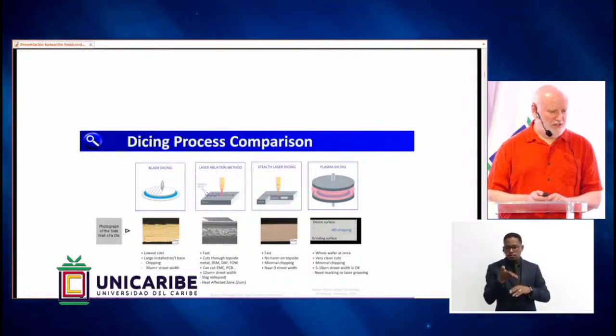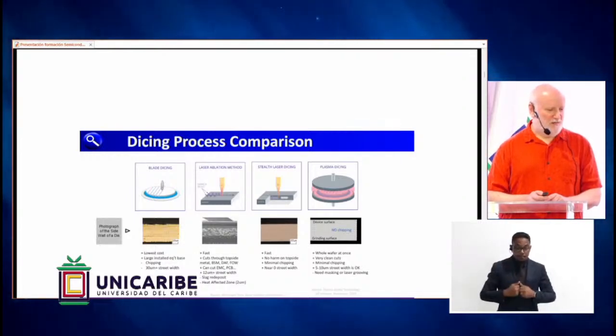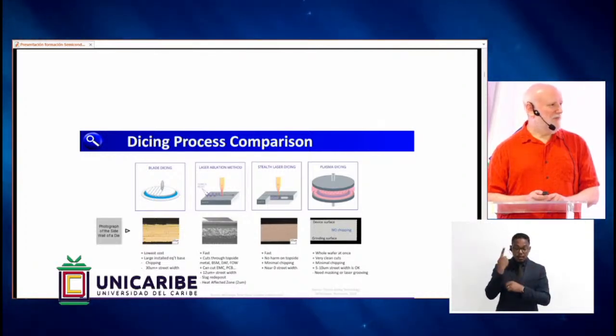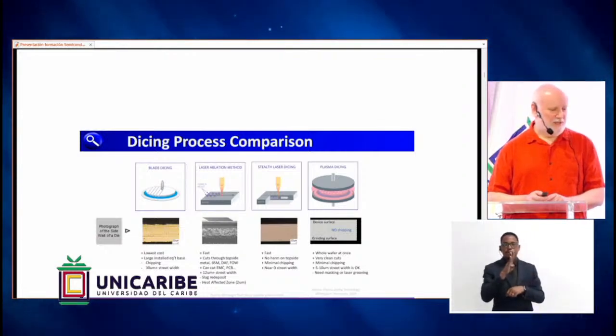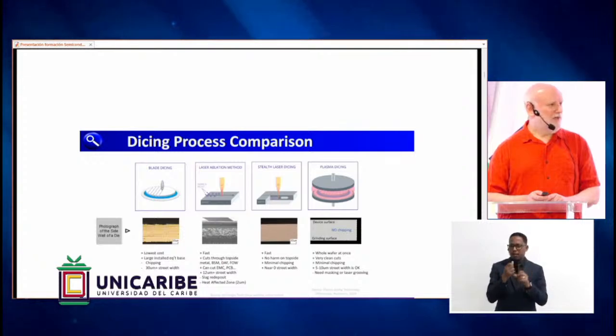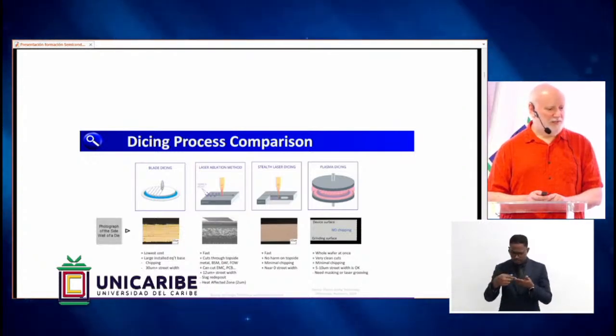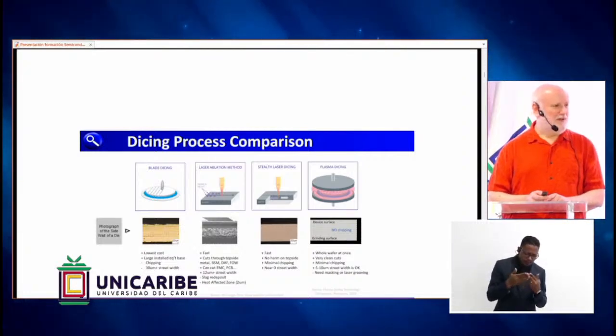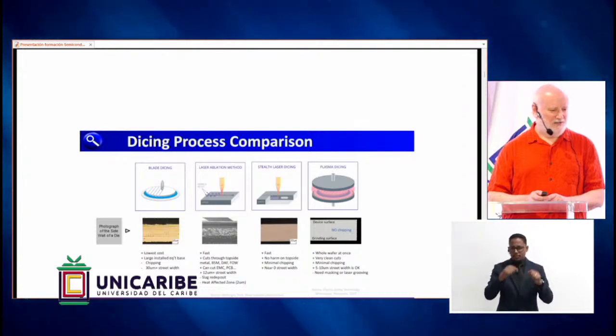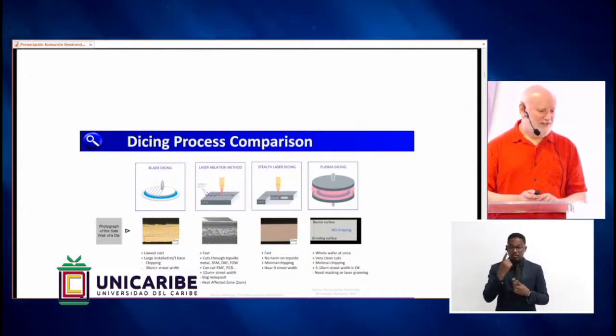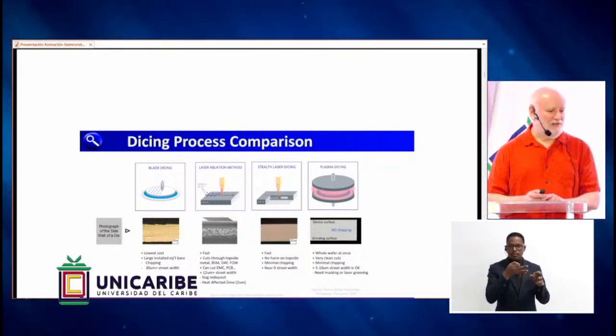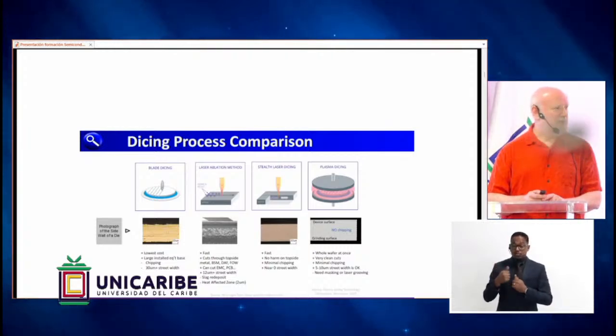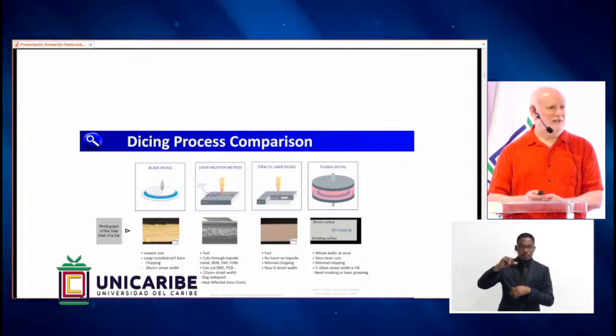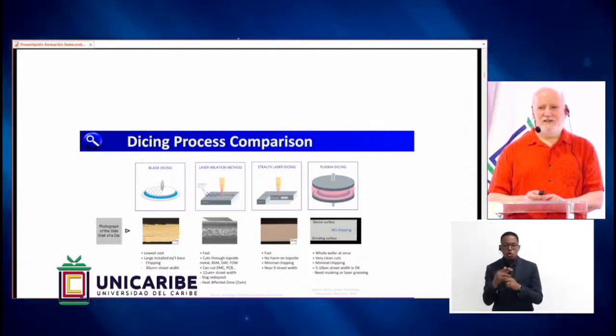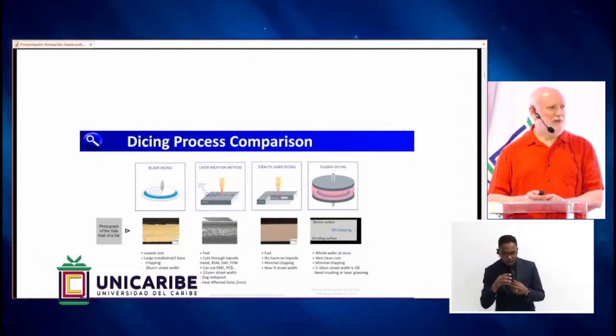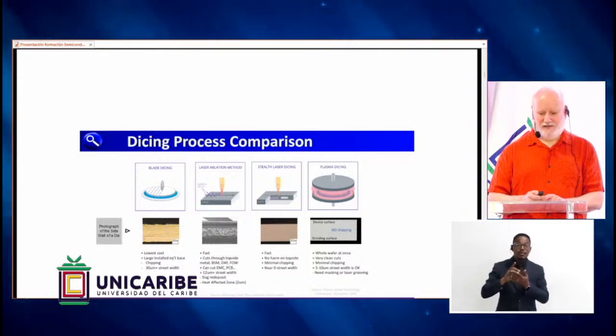And then this is just some comparison between the different dicing processes. Blade dicing or saw dicing is the most common because it's the least expensive and easiest to implement. But it has some issues in that the sides of the chip sometimes are rough, and that can lead to problems of chipping and cracking. Laser ablation is another method, but leaves a lot of debris on the side of the chip. That can also be a problem. The stealth dicing is quite a nice process. The saw street is very narrow, and the edge quality is very high, but it's a little bit more expensive process. And then plasma dicing, likewise, has small saw streets and very nice sides and edges of the wafer or chips when you're done, but the big problem there is you need a mask. If you didn't have a mask, you would etch everything on the wafer.